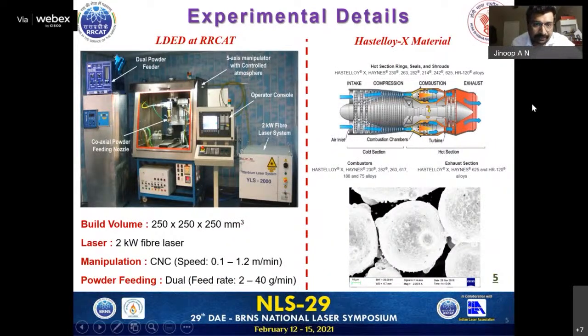So this is an LDED system that is developed at RRCAT. It's an in-house system which uses a 2 kilowatt fiber laser and a build volume of 250 by 250 by 250 mm cube. It has CNC manipulation and dual powder feeding. The material used for the study is Hastelloy, which is a nickel superalloy used for power sector applications and high temperature properties. It has good mechanical properties at high temperature and oxidation and corrosion resistance. There's a reason why this material is selected for this particular project. The powder used for the deposition in this process is spherical powder, sized in the range of 45 to 105 micrometer.